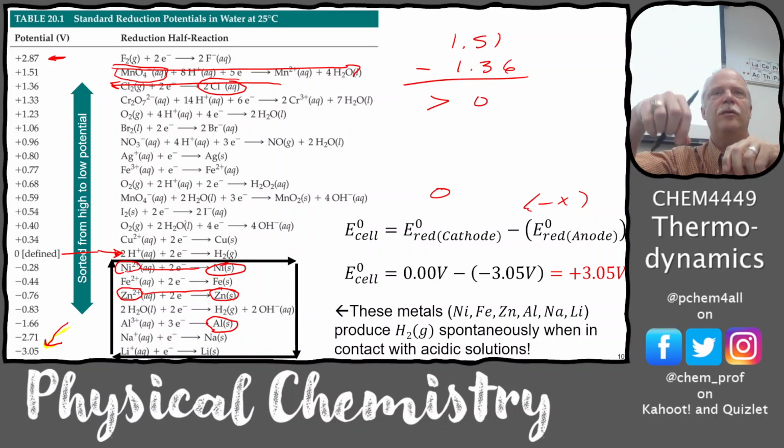We can just put the aluminum in, coat it with zinc, that dissolves off the oxide layer, and then we put it in nickel, and we plate nickel onto aluminum. A nickel surface is less reactive, so it's going to be a better coating for that aluminum.